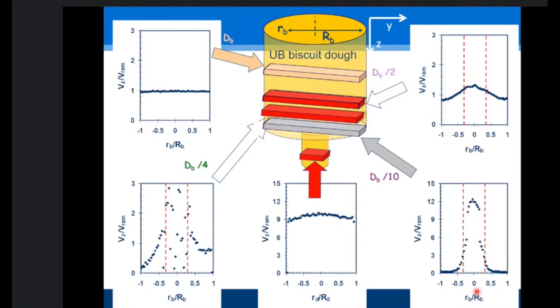So what do we see here? We see that wall slip is a reality in these sort of systems. We can see that the velocity is quite complex, and at this slice it's really noisy, and that tells you something about the pastes, and secondly, about how good these measurements were back in 2003, 2004. Now, MRI is really nice if your material is compatible with an MRI system. The one thing about MRI is you don't really want any metal anywhere near it. And some of the systems I'll show you won't work in MRI systems.